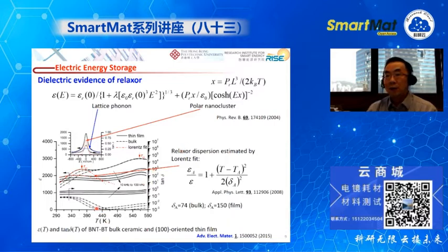And from the analysis of the dielectric spectra, we can also provide additional evidence. For example, this is the dielectric constant as a function of temperature. We can use this Lorentz fit to fit this dielectric spectrum, and from the fitting, we can find this delta A is larger for the thin film sample as compared to the bulk sample. So this means in our thin film sample, we have more relaxor dispersion.